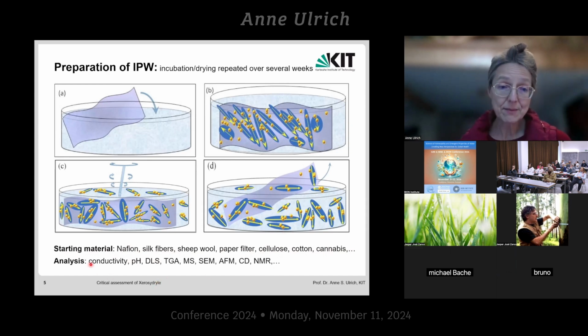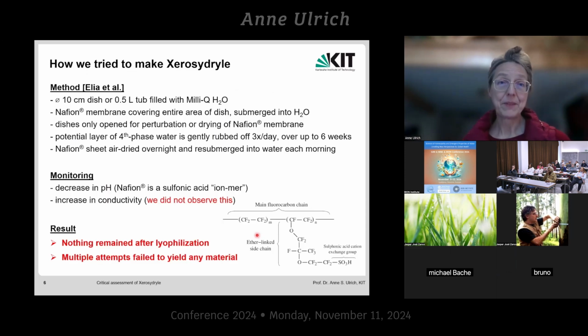The analysis follows conductivity changes, pH, light scattering, thermal gravimetric analysis, mass spec, scanning electron microscopy, atomic force microscopy, circular dichroism. We wanted to contribute the NMR. So this really seemed to be a very established topic. However, we did not manage to make any Xerosydryle under sterile conditions.